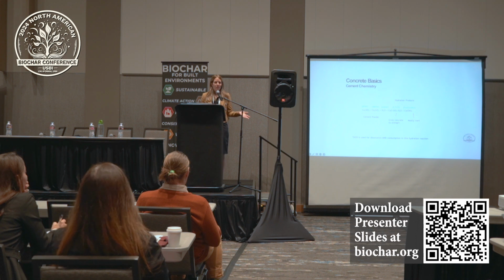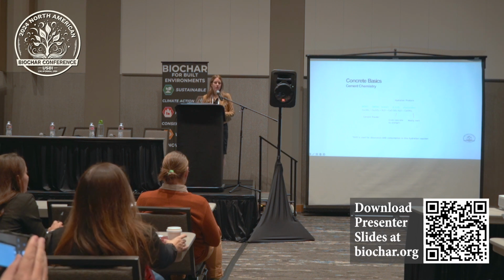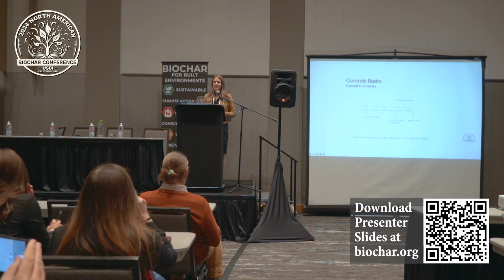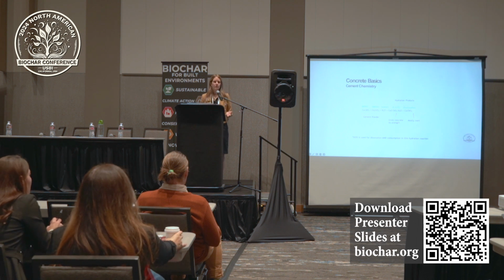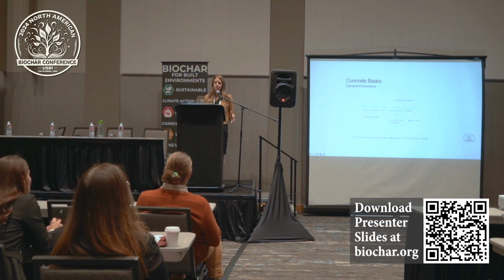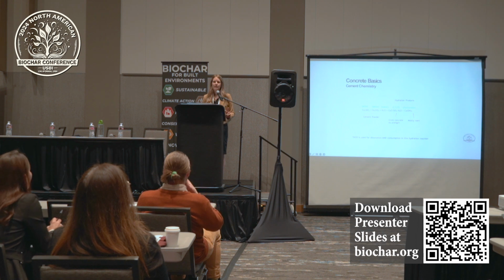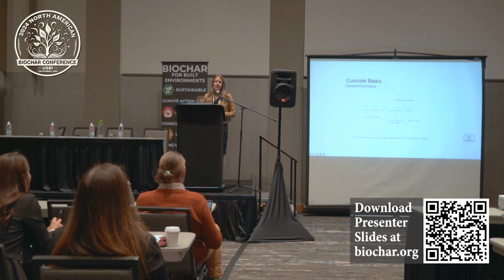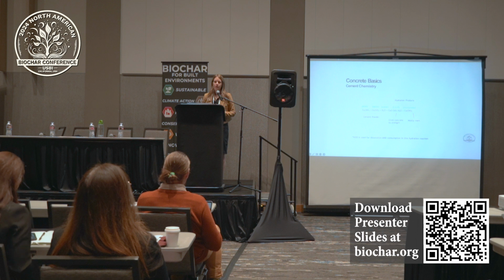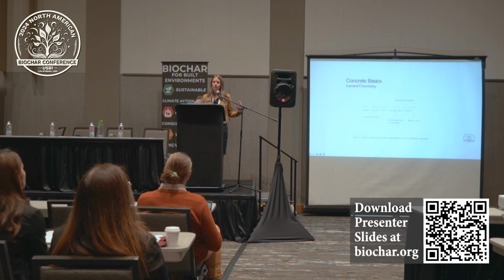I also thought it would be prudent to cover a little bit of cement chemistry. I'll mention that in the presentation as well. So when we put a dry cement powder into water, we get a chemical reaction. It's something called a precipitation reaction, where we dissolve the cement powder, the ions go into solution, recombined with water molecules to form hydration products. So we call this cement hydration. The two main hydration products that we get from this reaction is something called CSH, it's calcium silicate hydrate, and calcium hydroxide. The calcium silicate hydrate, or CSH, is the glue that binds the concrete together.